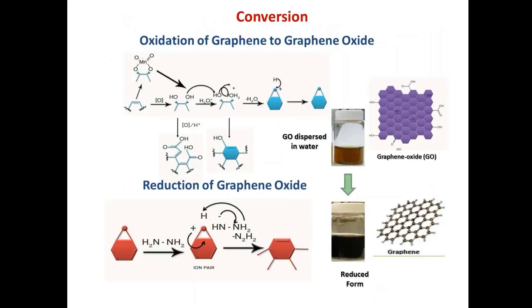On the other hand, if you want to get back the more conducting form, you introduce a reducing agent such as hydrazine, which converts the graphene oxide to the more conducting form of graphene, as shown in this picture, going from a brown colored solution to a dark black colored solution, which indicates a more conducting form, graphene.